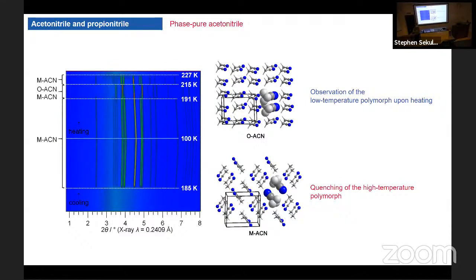And the reason why we do not see that is strange, but not that strange. It's just kinetically trapped, and we have the high temperature form being stabilized at low temperatures. As we're heating up, we are giving the system a little bit of a nudge, so it can really go back and get this phase transformation to the low temperature form, then another phase transformation to the high temperature form. So it is a little bit messy here, and then finally we have melting. What we'll learn from this experiment is that, sure, we have the high temperature and the low temperature form, but there can be a switch between them based on whether the crystallization is under more kinetic or thermodynamic control.